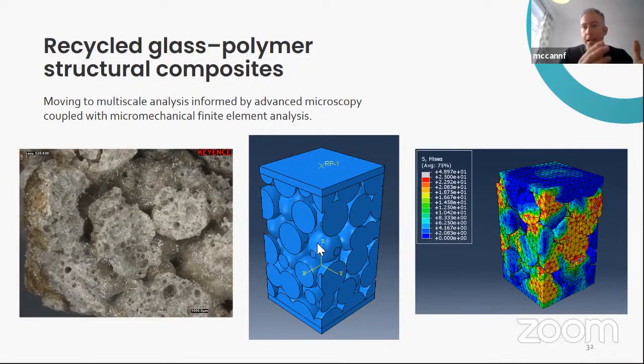Okay, so varying the sizes and the spacings based on the statistical distributions that were measured by the microscope. And then this is just some trial runs that I've done lately. We can then see the very, very local stress distributions within the matrix. And the idea here is that we want to manifest the macro scale behavior that we're seeing from the tests here by using this micromechanical analysis. And so far, it's actually going quite well.